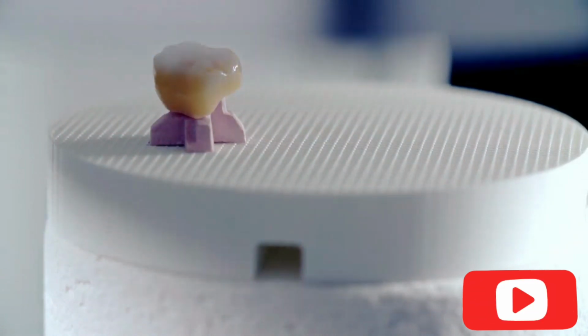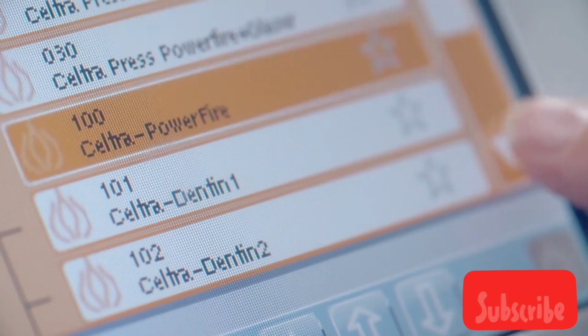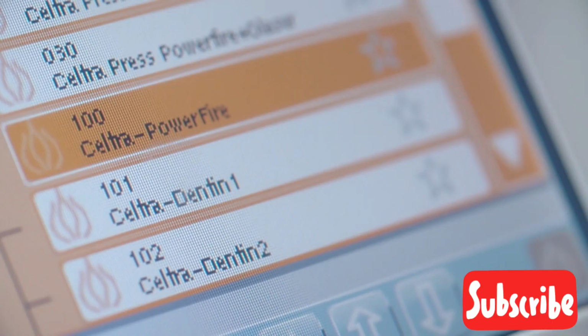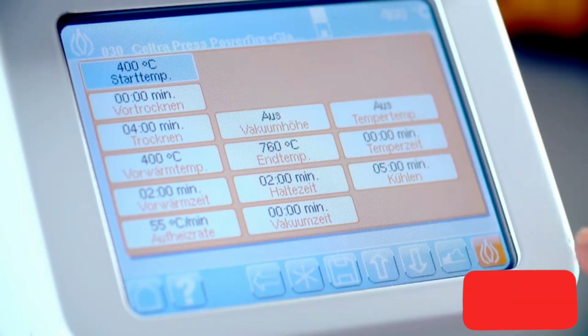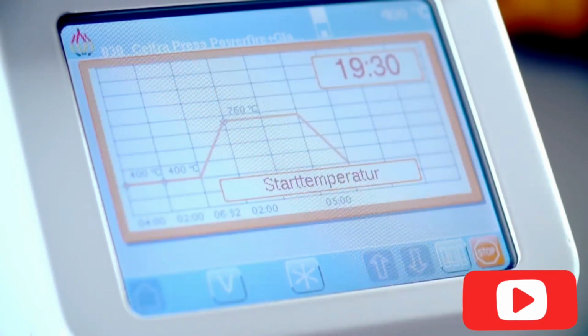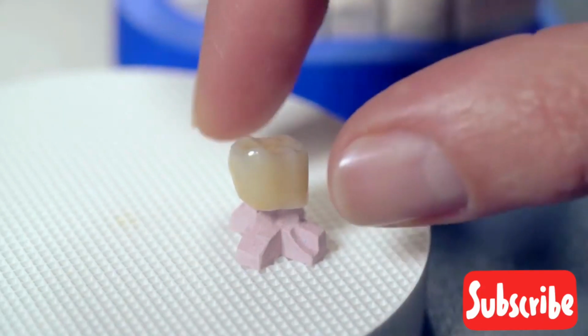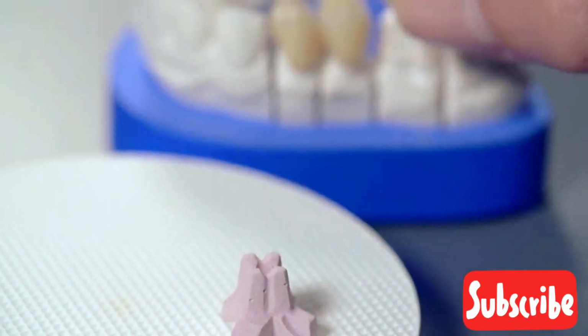A special feature is the power firing step. Power firing increases the strength of the Celtra Press restoration to more than 500 megapascal. For monolithic restorations, this step is already included in the glaze and stain firing cycle. After complete cooling, the shade is checked.